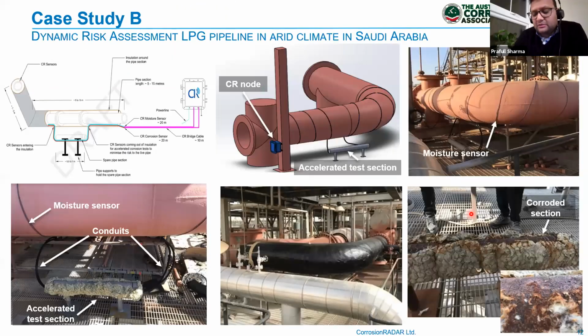So that's a very good question. Normally, we would suggest that because we are monitoring the pipe surface, it should be close to the pipe surface. For the operation, that's not a necessary condition, but it's an ideal condition if we can put it on top of the surface. However, there is a galvanic disconnection between this asset and the sensor because there is a plastic sleeve between them. So the ideal location, even with foam glass insulation, which I'm showing here as an example, is the sensor directly on the asset surface and then the foam glass insulation. Because the foam glass insulation is a closed cell. So that's an ideal condition for installation.